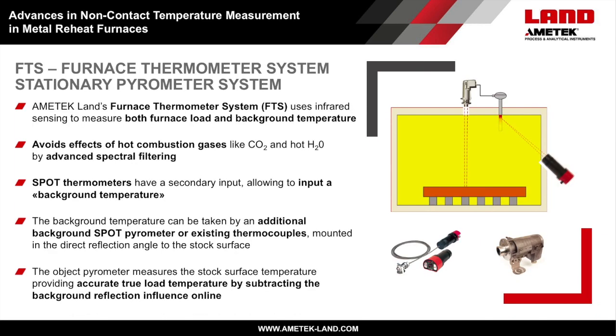The Land FTS is a reliable furnace temperature measuring system based on spot pyrometers. Providing advanced spectral filtering, these pyrometers avoid any effects of hot combustion gases like CO2 or water. With the spot thermometer secondary input, a background temperature can be directly fed back to the instrument for continuous background compensation. The background temperature can be taken by an additional background spot pyrometer, measuring the refractory temperature. See picture at the upper right side of the slide.